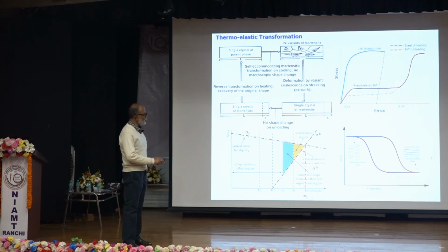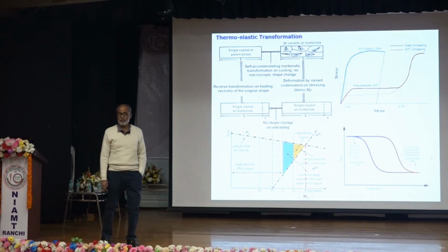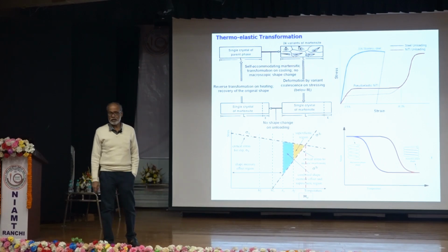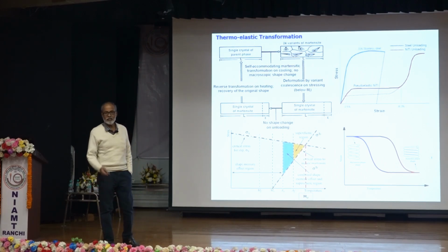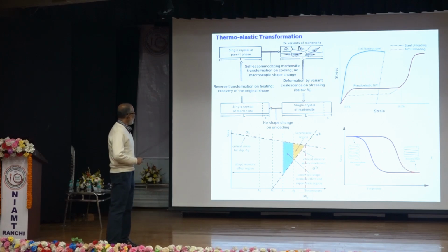Now, if you withdraw the stress from this point, you can see that this much strain can be recovered. It is about 8%. So you can recover about 8% strain, which is distinct, not available in other materials. Here we have seen this shape recovery or shape memory occurs only when you heat it. So it is one direction. So this we call one-way shape memory. It is from martensite to austenite.